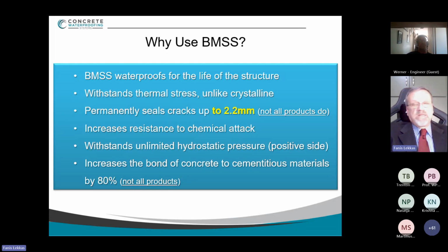Sealing the porosity of the concrete completely means that we are essentially protecting the steel rebar against corrosion. That means that you can even take the corrosion inhibitor out of the design mix. Some consultants say, is this a corrosion inhibitor? And we say, no, it's not a corrosion inhibitor. The corrosion inhibitor is just an admixture that will wrap around the steel rebar, protecting it passively against chlorides. Here the technology is different. It is the porosity of the concrete which is completely shut off to the entrance of chlorides and sulfates, which means that you do not need to use it.